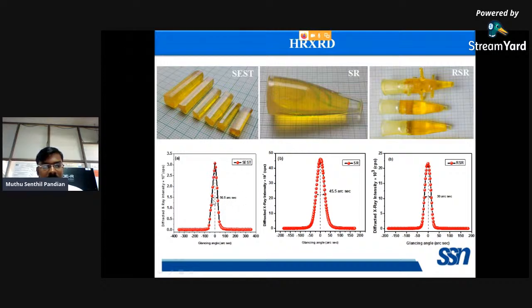The FWHM value of the conventional method grown crystal is 56.5 arc seconds. Under identical conditions, under identical purity, Merck GR 99.99 purity, under identical thickness, we have made all the experiments. But in the case of the SR method, we have avoided the growth sector boundaries, solvent inclusion, milky opaque, everything we have avoided. So the FWHM of the SR method grown crystal is 45.5 arc seconds. So in order to reduce the impurities content present in the SR method grown crystals, we have made the RSR method. The FWHM of this RSR method is 30 arc seconds. So from this measurement, we can easily conclude that the crystal grown by RSR method is very, very superior compared to the SR and the conventional method grown crystals.